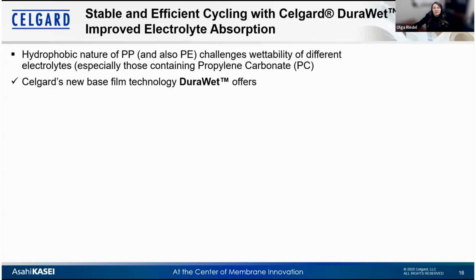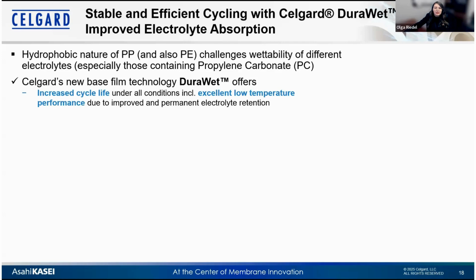There are also several publications now on how electrolyte motion due to electrode expansion can lead to decreased cycle life. There are publications by Jeff Dahn, but also some publications by BMW, also on the concentration gradient that it creates in the electrolyte. Part of the challenge here is also the reabsorption of the electrolyte into the pore structure of the separator. And here at Celgard, we have a new technology for that called DuraWet, that can increase the cycle life and also the low temperature behavior, since the base film is inherently retaining the electrolyte.